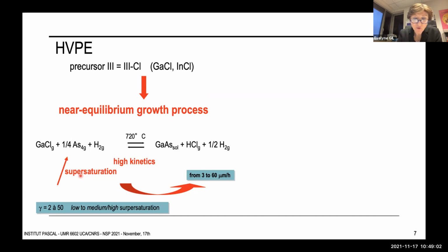And on decreasing the supersaturation, for instance, by the use of additional HCl in the vapor phase, reversible processes occur at the vapor-solid interface due to the volatility of the chlorides. And that is supposed to characterize a process for which the operator can really play with the reaction with respect to equilibrium. Then, a wide range of condensation rates from 3 to 60 microns per hour can be set for standard conditions, and for supersaturation ranging from 2 to more than 50.